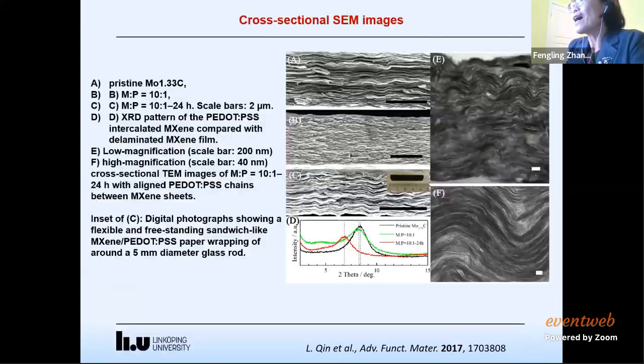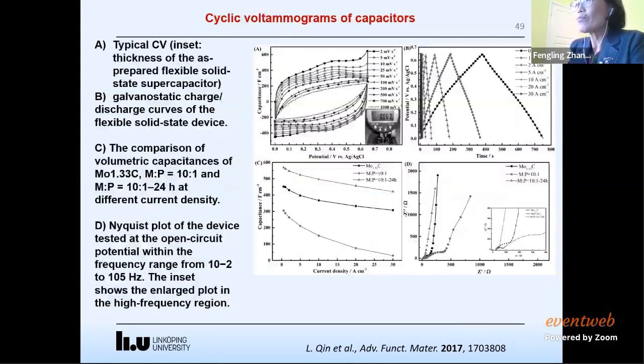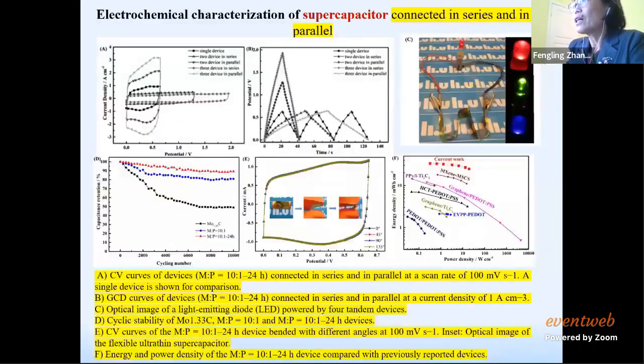Here I want to show you how the film looks like. This TEM shows that the mixed MXene and PEDOT:PSS make a lot of space between layers. That's the reason they can store more charge and increase the capacitance. This is from the film, and this is from the capacitor, a device made with electrodes. Here is for the different connections, because a single capacitor does not meet the requirement for the application. So we tried to connect them in series and in parallel, and then we got different performance.